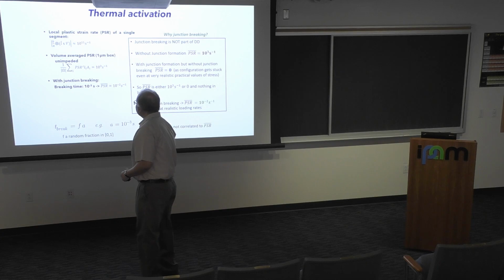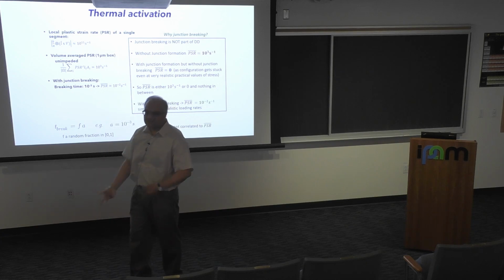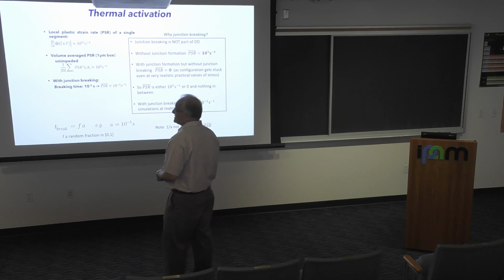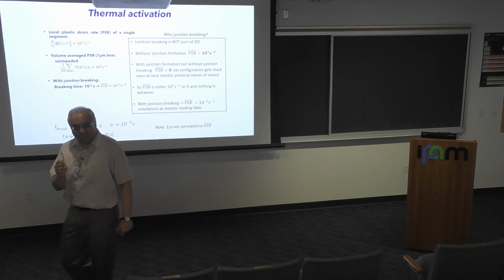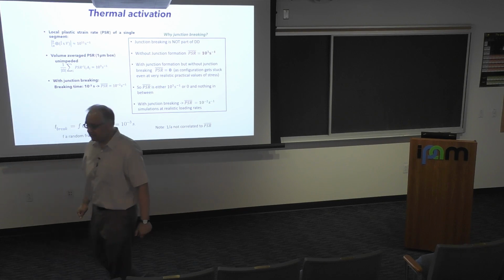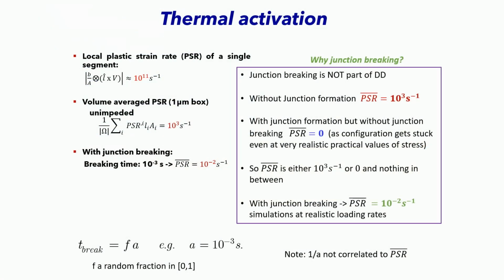All right, very good. So now what can you do? So then you say, okay, but then the junctions will form. But this is what happens. Junction breaking is not a part of DD as such. Junctions mean there are dislocation lines, there are rules, and they get stuck, okay? But what do I mean by junction break? This is thermal activation, right? So at low enough stresses, like 20 MPa, 30 MPa, a single crystal of copper will yield at 17 MPa, let's say. You put 17 MPa on a DD or MD box, and nothing is going to happen. Okay?